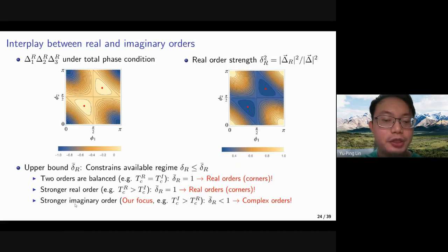However, if we have a stronger imaginary order, which is our focus, for example, we could have its critical temperature be higher than the real order's, then the maximal real order strength we could have would now be smaller than 1. In this case, we are pushed into the bulk of the phase diagram, or you can say we are pushed into the higher free energy regimes. And although the functional forms of the two diagrams might be different, the contours with equal real order strength will have the same energy. That is, the contours in the two diagrams will be the same.